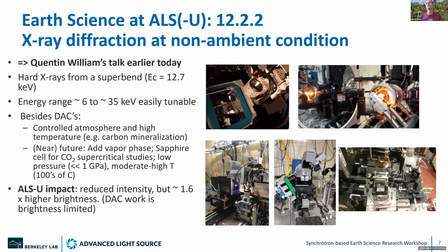A particularly successful example was the catalyst community, which approached us with the need to do in situ X-ray diffraction under controlled atmosphere and high temperature. Together with them, we developed this lamp heater, which is now used across the field and is very successful. It can definitely also be used for earth science applications, for example, carbon mineralization, especially if, as we plan, we add a quantitative vapor phase, or we revive a sapphire cell, which allows us to go to CO2 supercritical conditions.